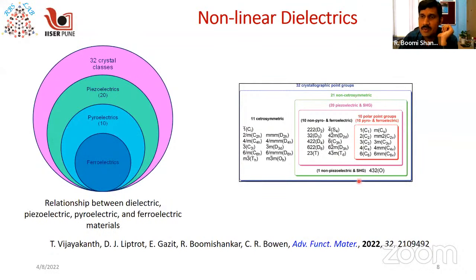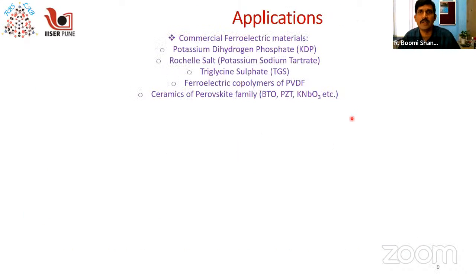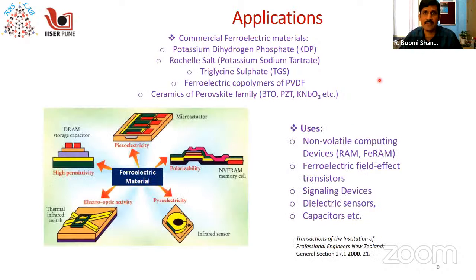Okay, which means that as a synthetic chemist or a synthetic materials person, it is very challenging to design ferroelectric materials, because you should be a little lucky or have some extreme idea about controlling the symmetry of the system to be able to realize these properties. Okay, so with that background, let me now go to the ferroelectric material story. The commercial ferroelectric materials are potassium dihydrogen phosphate, sodium potassium tartrate, which is called Rochelle salt, triglycine sulfate, and there are a lot of ferroelectric copolymers such as polyvinylidene fluoride. These are all known. Of course the best among all are the ceramics of the perovskite family, for example, barium titanate, lead zirconate titanate, potassium niobate, and so on.